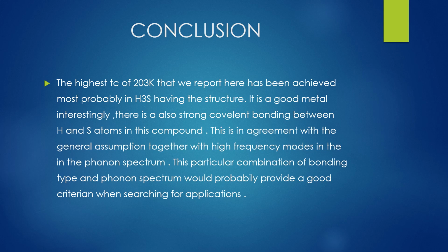So basically, year by year after 1986, the critical temperature has increased. The highest critical temperature is 203 Kelvin. It is a good metal. Interestingly, there is also strong covalent bonding between H and S atoms in the compound, which is in agreement with the general assumption, together with high frequency modes in the phonon spectrum. This particular combination of bonding type and phonon spectrum would probably provide a good criterion when searching for applications.